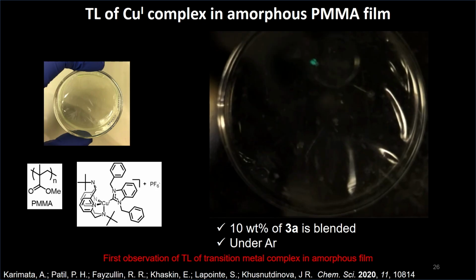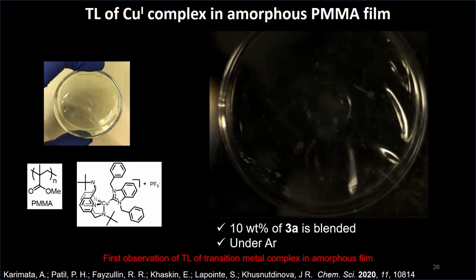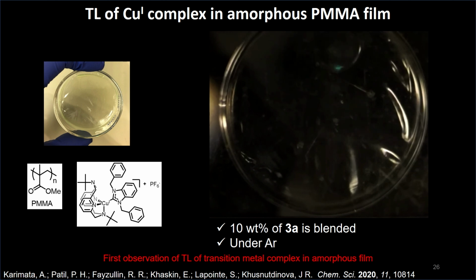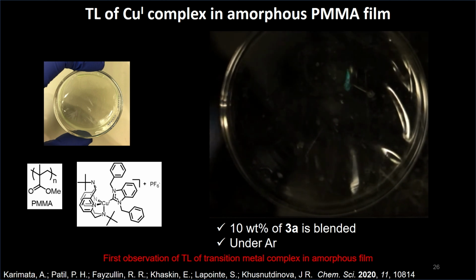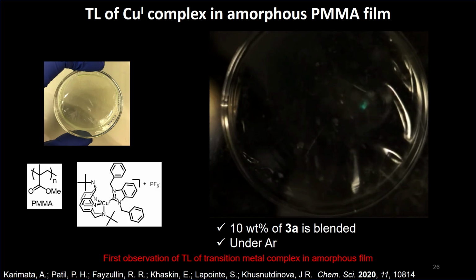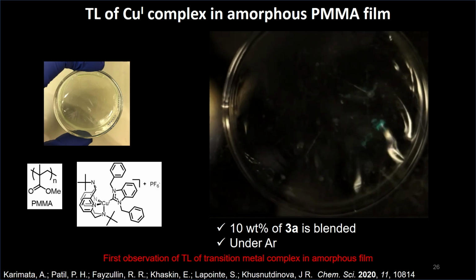This gave us an idea, although it's not directly related. Maybe we should try and translate this property from the crystalline state to the amorphous state. And then what we did is that we blended our complexes in the polymethyl methacrylate in low amounts, and we made the film. Then when we rub this film under argon, in this case, with the glass rod or the silicon rubber rod, we see the light emission in response to this activation.